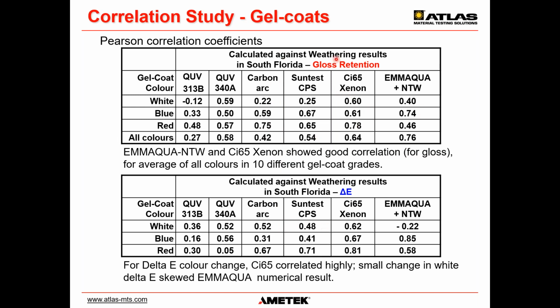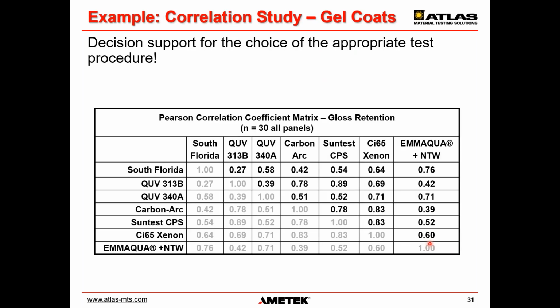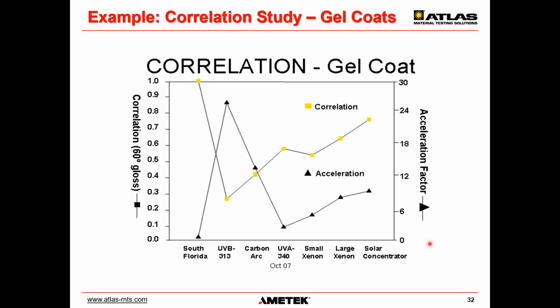Xenon arc devices, the smaller xenon arc device with limited temperature control, limited humidity control, really in the middle range. The larger xenon weatherometer in that example showed the best results actually of the artificial methods. And overall, the best results actually could be achieved with the EMMAQUA, with the solar concentrators. Not for white. The white color change showed a little bit of discoloration, which was a little bit off, but the other colors showed the best color change. Yeah, we did also a cross correlation between the different methods, but I don't want to go into detail here.